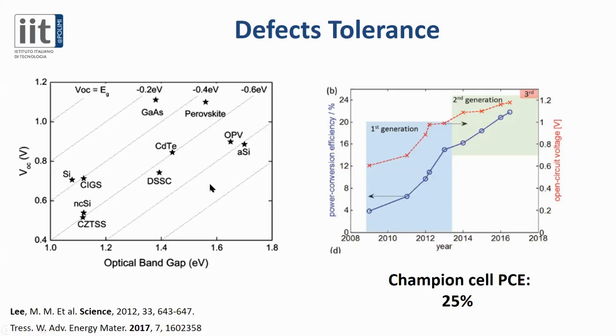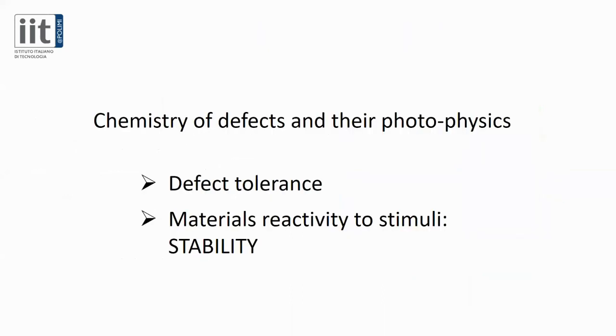And you can see that in perovskite, since the beginning, this loss was very minimal. And today, we are able to fabricate champion photovoltaic cells with power conversion efficiencies of the order of 25%. This means that it is close to what silicon solar cells are showing in the lab. Now, these materials can be synthesized and processed at very low cost with very simple methodologies, which is prone to scale up.